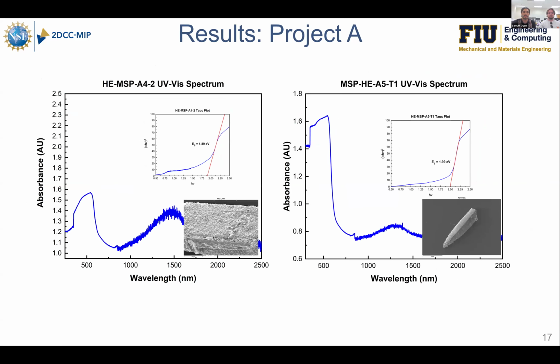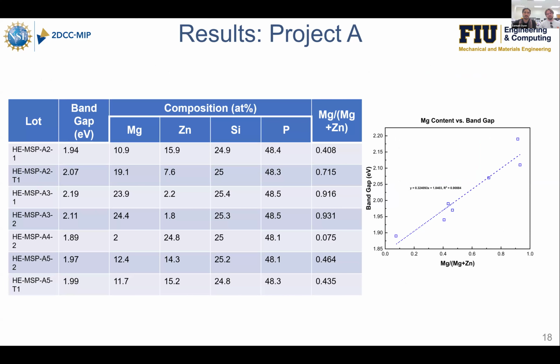Here are a few more crystals, the A4 and A5 samples, and again, we see clear absorbance in the visible spectra. To compile all of these results, we only highlighted a few of the UV-vis spectra, but we did get a few more crystals from that. And these are compositional results after polishing.